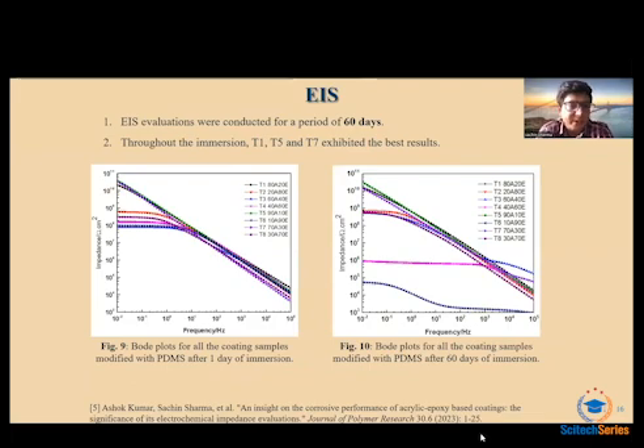So let's look at the EIS evaluations. The EIS evaluations were conducted over a period of 60 days. So the sample was exposed to seawater conditions, 3.5 weight percentage NaCl, and the values were measured over a period of 60 days. And we can see figure 9, which is the Bode plots results after the first day of immersion, and we can see that the green one, which is the T5, exhibited the best results, along with T1 and T7, which again contain the highest content of acrylic ratio.